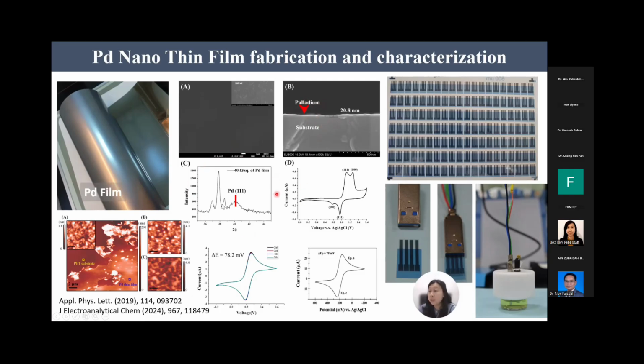Here shows the XRD spectrum of a palladium nano thin film electrode, and these are AFM images of the boundary between the palladium nano thin film and the PET substrate. So we also ran electrochemical studies like the CV curve to study the electrochemical stability and how stable this electrode is. You can see here, this is the PET, this is the palladium nano thin film on the PET substrate. We use it as a working electrode, so you can put 4 samples and you can detect 4 samples using one.